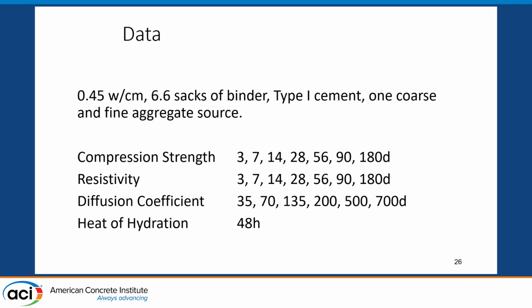We're going to use a 0.45 water-cement ratio, 6.6 sacks, which is a lot of binder, but we don't want to have any admixtures. Why? Because that may complicate things, and we're not ready for that right now. We just want to understand how these fly ashes perform on a comparative basis. We're going to use 1 cement, we're expanding that, 1 coarse aggregate, 1 fine aggregate, but we're looking at all this information: compressive strength from 3 days to 180 days.